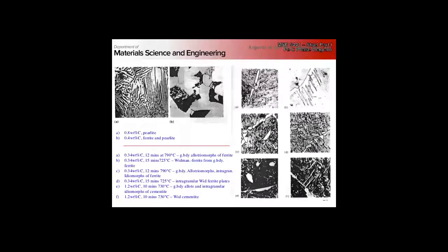So this is just sort of a preview. If we're real close to eutectoid, we get full, nice, clean pearlite. If we're hypo, we get a mixture of ferrite and pearlite. Right. Depending on what our heat treatment is, or our exact cooling schedule, we can get a whole bunch of stuff, right?